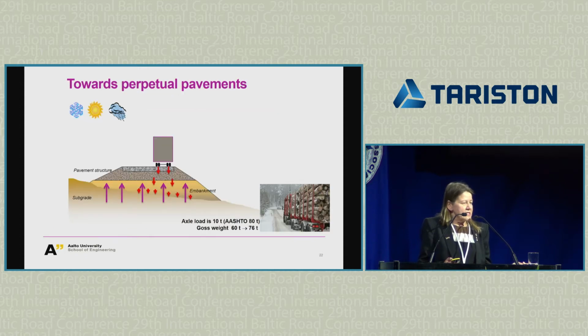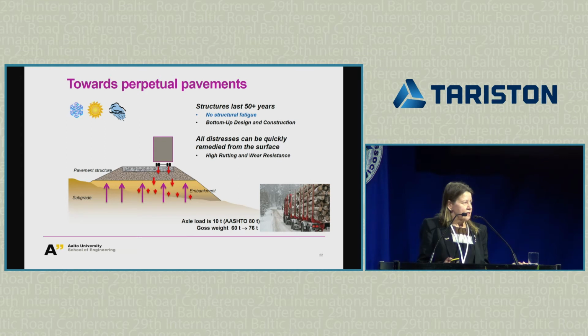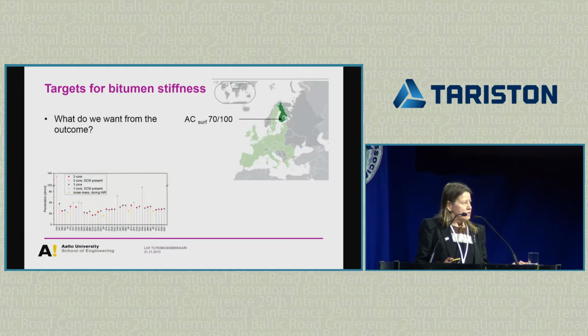So, well, the idea is towards these perpetual pavements, very heavy base courses, and the only thing we want to do is fix the surface layers. The question is really what we are expecting from the surface layers, what the life expectancy is. In Finland, when we have these studded tires, the cycle is very fast, so between 6-7 years we need to go and do the resurfacing. So we really talk about bitumen stiffness when we talk about targets, and then the question is, what do we want from the outcome? Well, in southern Finland, a very typical surface mix uses 70-100 bitumen.